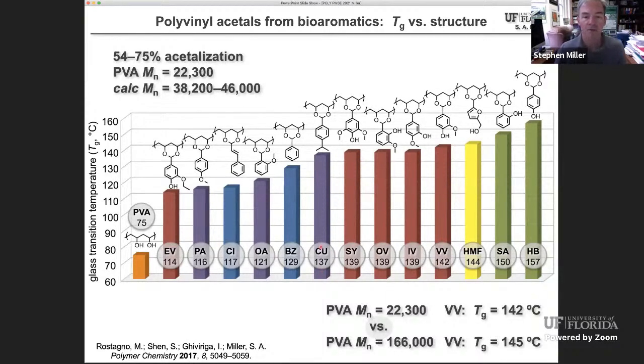So here is a graphic showing the attachment of a wider variety of bio-based aromatic aldehydes to polyvinyl alcohol. In all cases, we see an increase in the glass transition temperature. Vanillin is here, VV at 142. So again, there's a considerable boost in the glass transition temperature. You can make some correlations with the structures of these. So there's some hydrogen bonding that's residual in some of them. Some of them have some flexible groups like this ethoxy group, which probably introduces some free volume, which gives you the lowest glass transition temperature of this series. But nonetheless, we can see that we are able to boost the glass transition temperature into a realm that's quite useful, right? Most of these could in principle hold very hot water.